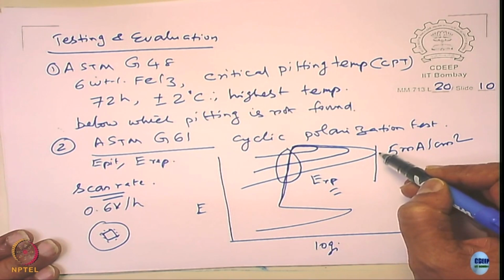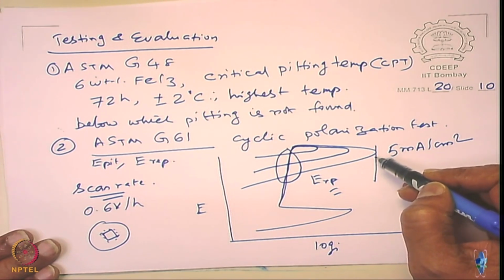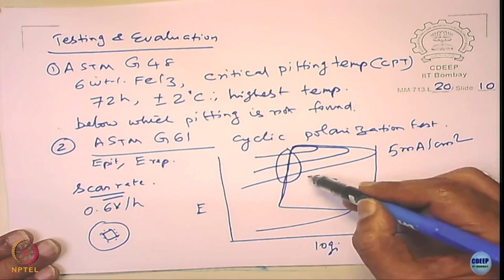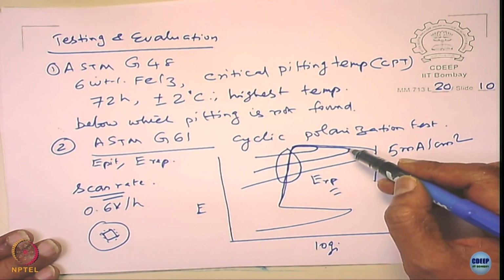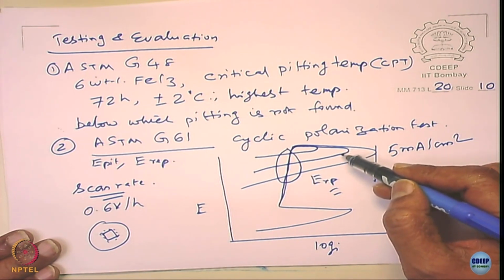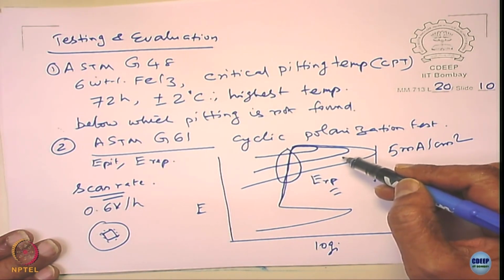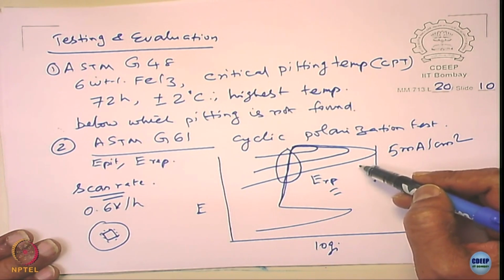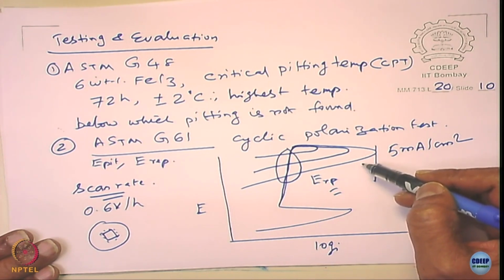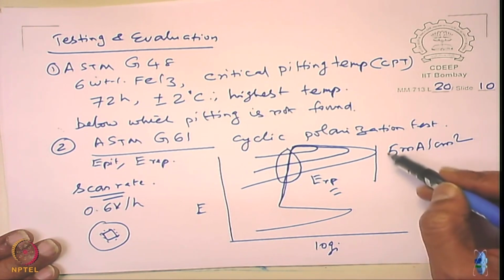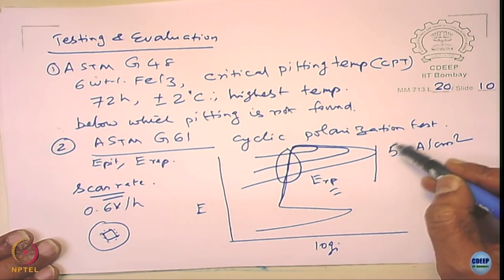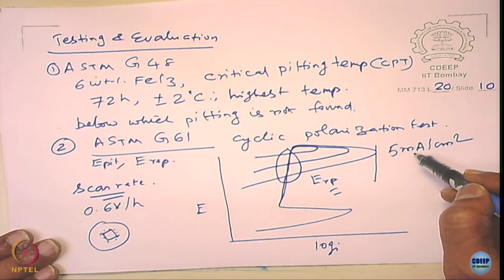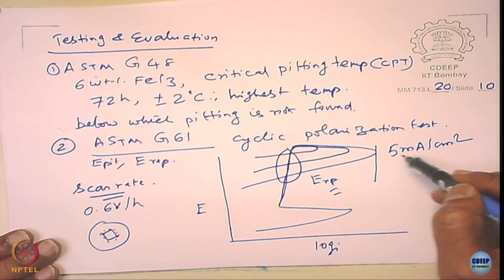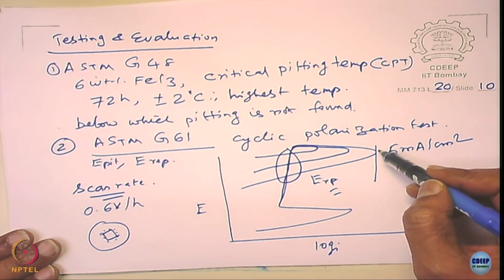If you apply more current, the pit becomes deeper, it becomes difficult to repassivate. If the current is lower, the pit is shallow, it is easy to repassivate. So repassivation of the pit does not depend only on the metal, but also depends upon the depth of the pit. But what they have found here is, if you are going to apply 5 milliamperes and above, it is not going to depend upon this current.